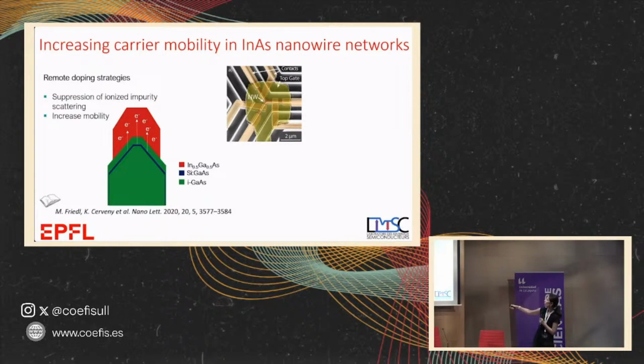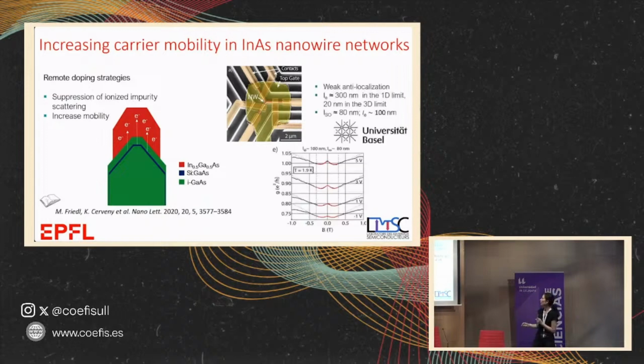So we did this. And then we made a device in collaboration with our colleagues in Basel, where we made the transport through this junction, so really the most difficult case. And we see a phenomenon as a function of the magnetic field, which is called weak antilocalization. And this is a sign that you have interference between the electrons that have, along the path, different spin. And this tells us that we start having coherent transport, so we are going towards having these electrons that behave more like ray optics than like electrons in a metal.